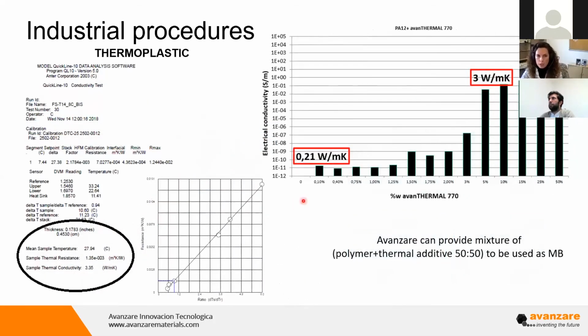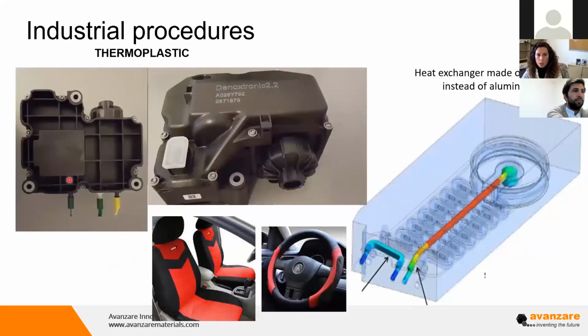In these cases, if the customer needs it, we also prepare a master batch with a high quantity of our material. This master batch can be 3, 4 watts per meter Kelvin, depending on the processing and on the starting polymer, and of course with high electrical conductivity. We can provide this master batch because in some applications such high thermal conductivity is not required, and one or more watts per meter Kelvin can be enough. So the user can employ this master batch in the process to prepare a final material, as for example this one, an injection-molded tank or heat exchanger made of polymer instead of aluminium, with some properties as, for example, the reduction in weight.